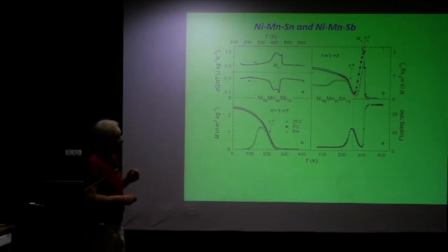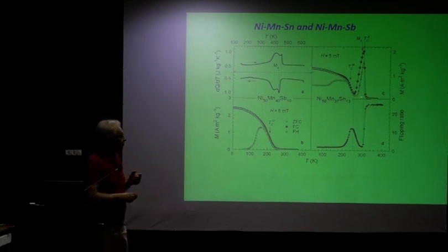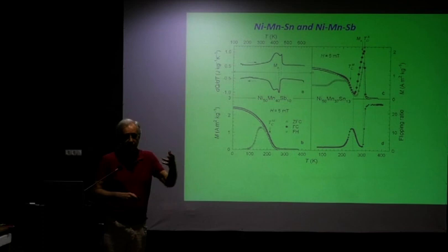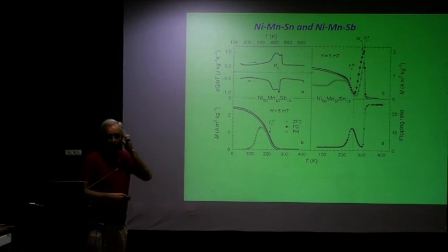And as you may recall, when we did the field dependence of the magnetization measurements, this showed some kind of a paramagnetic response, but there was some ferromagnetism in there still as well because there was a certain curvature over there. So the beam here is not fully depolarized, and the polarization recovers. And then what happens here? Then it starts dropping again. And it drops when it comes practically to this position over here. And then the beam is depolarized again.